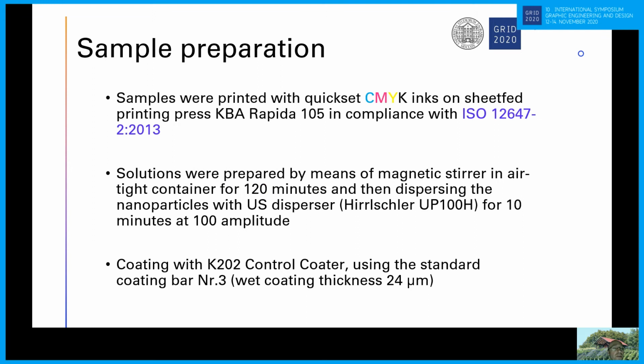And the preparation of samples was in two stages. One was made in a print house, which is PSO FOGRA certified, and the prepared samples were printed on the sheet-fed printing press KBA Rapida 105. We were using Quickset CMYK inks, and the printing was in compliance with the ISO 12647-2:2013 norm. That means that production and tone value increase and so on were highly determined, and it was under strict boundaries.